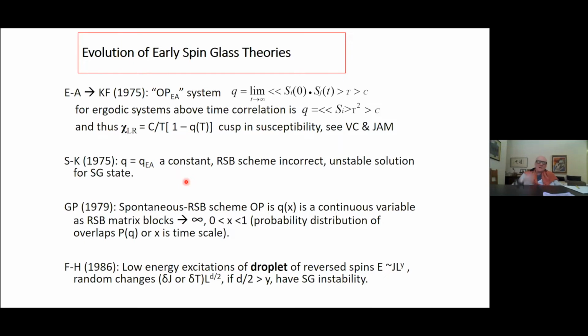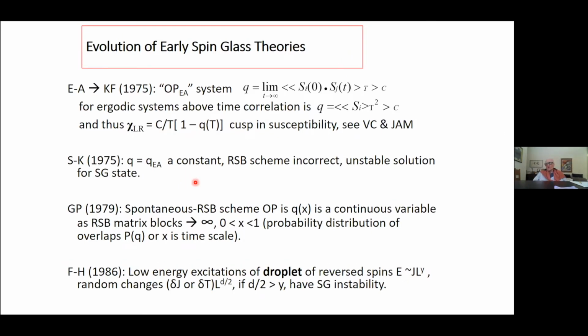However, after this publication came out, and as I said, there were approaching 4,000 citations, everybody, experimentalists, it was very amenable to experimentalists to look at what they're saying, at their susceptibility, specific heat, and compare with their phase diagram. We were all enthusiastic about this. However, in the intervening years, up to 5 years, many theorists began to look at this replica symmetry breaking scheme. And the conclusion, after much huffing and puffing, was it's incorrect. It gives unstable solutions for their spin glass state of infinitely interacting spins over the whole matrix. And so you had to take this with a grain of salt. Perhaps you get some experimental insight.